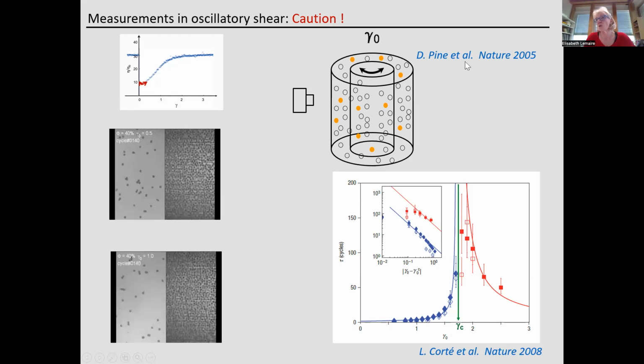This work has followed the work of Pine. It's almost the same group. And here they have reported the variation of the number of cycles that are necessary to obtain a stationary state. So that means that what I've shown you before is not obtained for the first cycles applied to the suspension, but these pictures have been taken when the suspension is in its steady state.